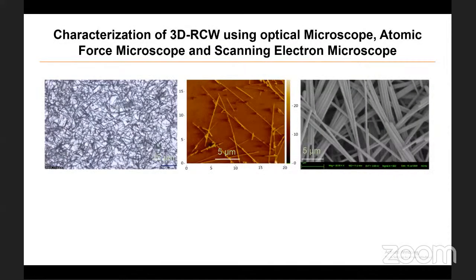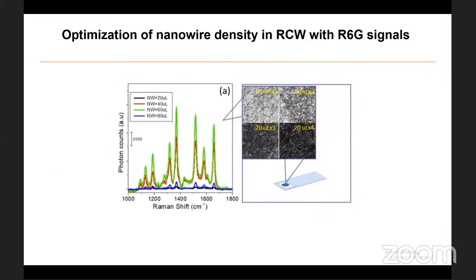We also characterized the 3D RCW nanostructure using optical microscopy, AFM, and SEM. The wood-pile nanostructure has many intersection points for hotspot generation in this chip. To evaluate the performance of the 3D RCW chip, a common standard chemical, rhodamine 6G, was used to test its Raman signal in different densities of nanowire in the chip. An optimized nanowire amount results in enhanced SERS response from R6G.